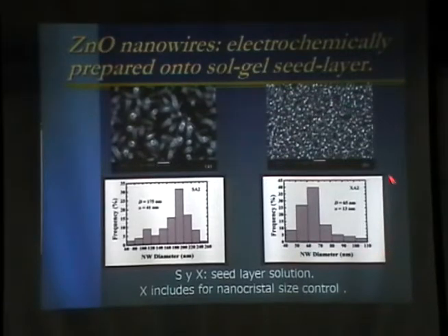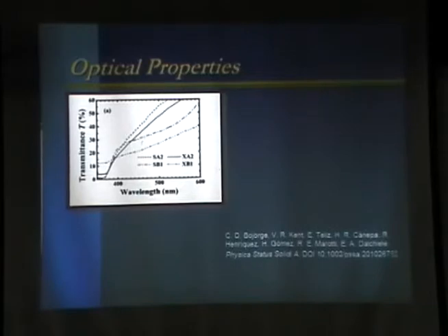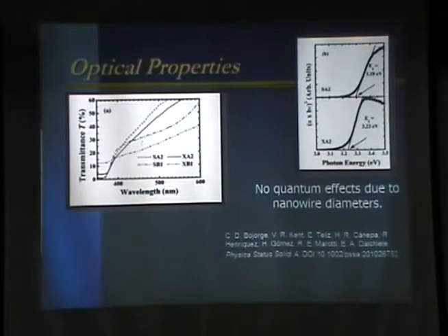In the case of this sample called X, there is some additive introduced in the solution that allows us to control the size of the nanocrystals, so the nanowires also have smaller diameters. These are optical transmittance spectra. In this case, there is no quantum effect. The band gap does not depend on the diameter of the wire. That is because the wires are on the order of hundreds or tens of nanometers, quite larger than